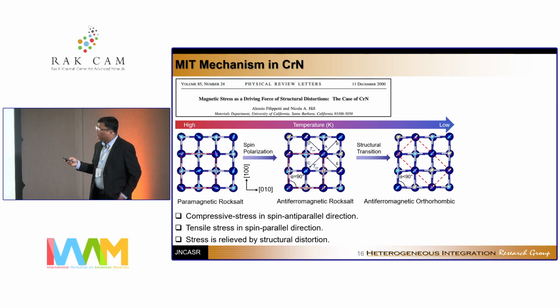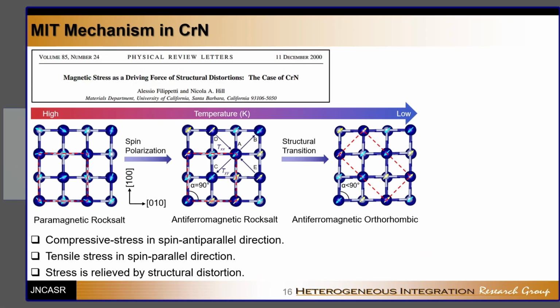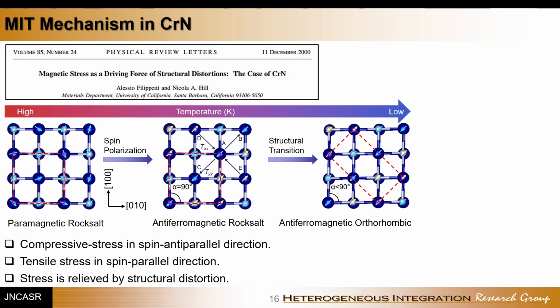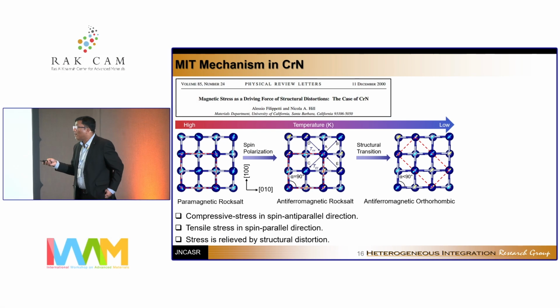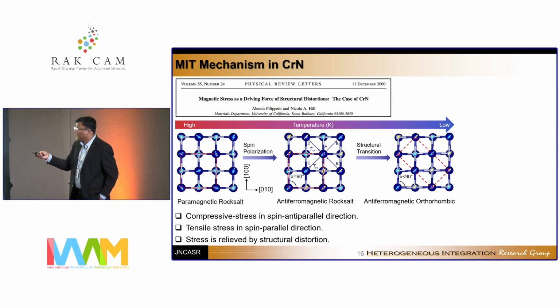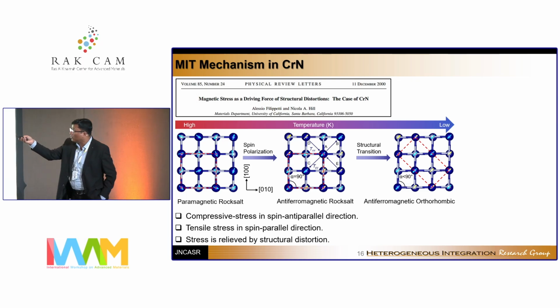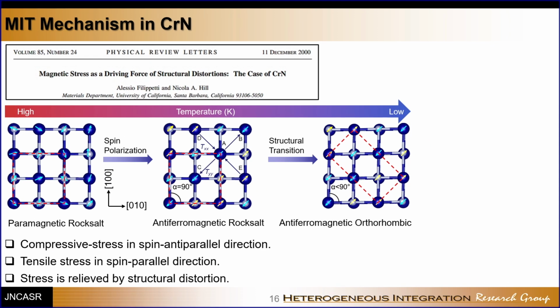And that is the point which Nicola Spaldin, some years back, had tried to explain: what is the origin behind this phase transition. So what she proposed with theoretical calculation is that in chromium nitride, as you come from high temperature to low temperature, first the spin alignment takes place. So paramagnetic spins basically align into an antiferromagnetic rock salt spin structure, but it's not just any orientation. You see there are two layers of ferromagnetic layer, then two layers of another ferromagnet, but then they are in opposite direction to each other. So basically 2 layers in one direction, 2 layers in the other direction.